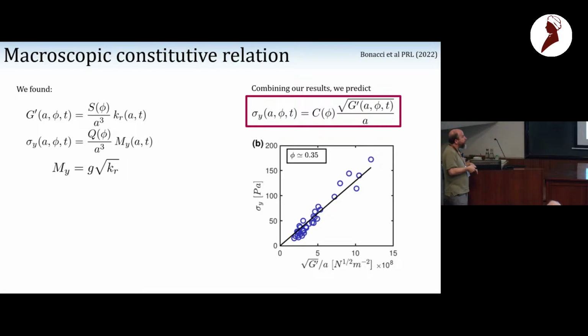Right. And another interest is that if you know this curve, by measuring the modulus you have an idea of your yield stress, which for industry is absolutely essential, because you can measure the yield stress without damaging. So that attracts attention from these people.